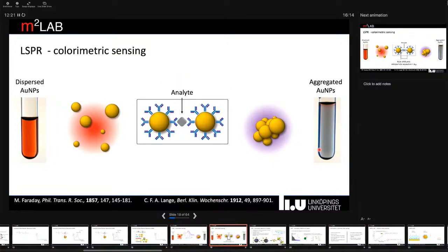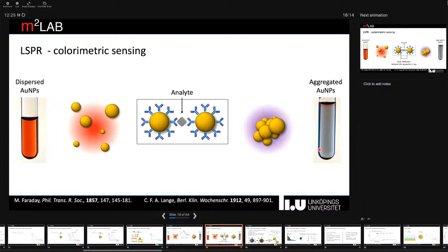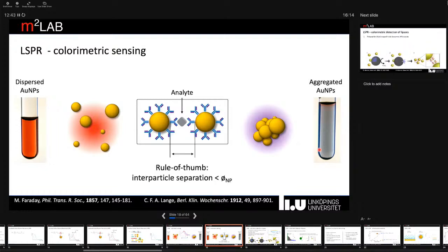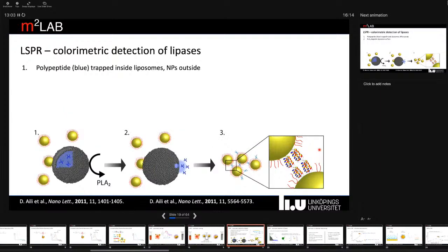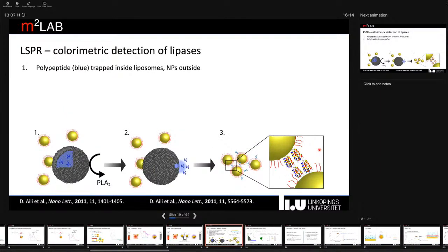But it can also be used for more specific biosensing, as we think of biosensing, where you actually have a biorecognition element that triggers aggregation or de-aggregation of particles as a result of binding of the analyte. And this can be done in many different ways. There are a few limitations, but one of the main ones is that you have to end up with particles that are close enough to get this optical coupling, which means they usually need to end up with a separation less than the diameter of the particles. We, and many others, have investigated various ways to use this phenomenon for biosensing.